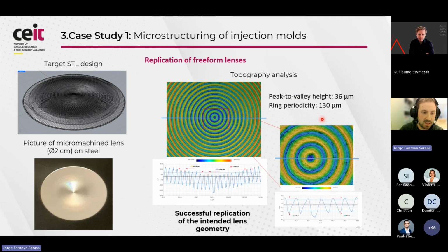And the false color means the difference in height. And you can see here focused on the center of the engraving. To give you an idea, there is a peak to valley height of around 36 micrometers and a periodicity in these rings of 130 micrometers. So in this case, we achieved close replication to the intended lens geometry.